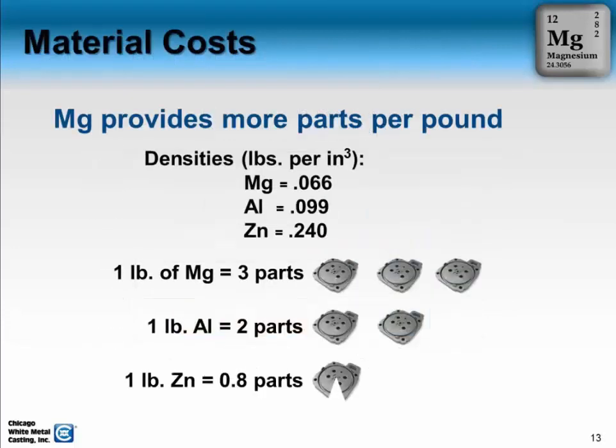The next factor to look at for any kind of economic standpoint is material costs, and the next couple of slides deal with that. So when you look at magnesium versus aluminum or zinc, obviously the density is much, much different for each. So it's just interesting to show the densities of each. Magnesium is 0.066 pounds per cubic inch. Aluminum is about 50% higher than that, and then zinc is much higher, about 0.24 pounds per cubic inch.